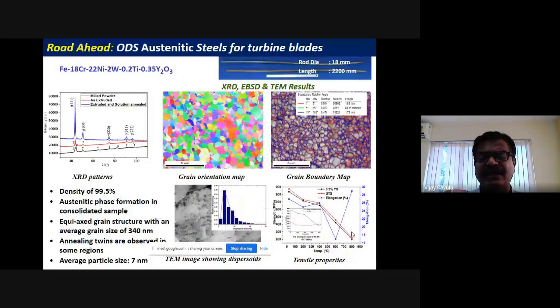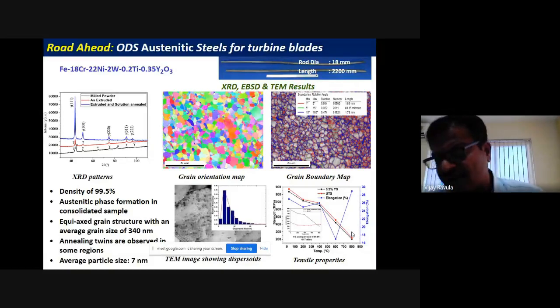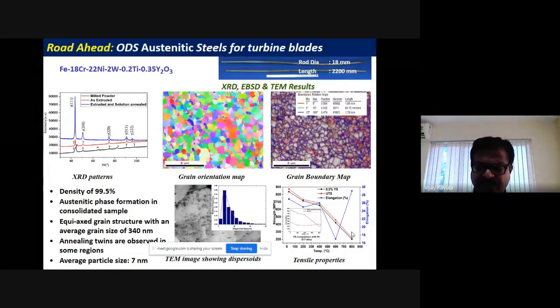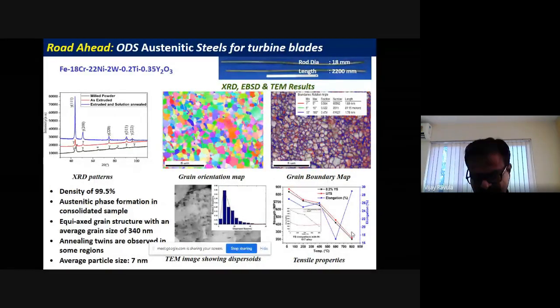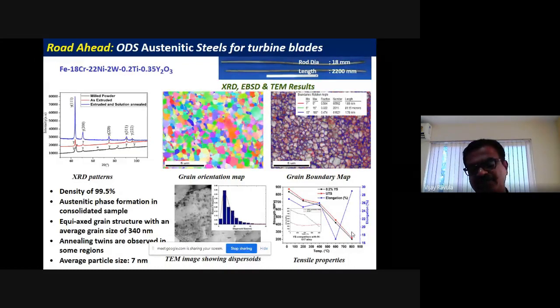And based on that, we are also looking at austenitic steels, because I was talking to you about 9 chrome, where the strength and all are okay, but the problem is they suffer from corrosion and oxidation resistance because of the lower chromium content. So if you want to use it even in gas turbines, where corrosion and oxidation are the biggest problems, we can always have austenitic steels, which have good oxidation and corrosion resistance. But austenitic steels cannot be used beyond 500 degrees centigrade. So when we put in oxide dispersions, then the strength can go up. So that's what we are working on: these austenitic steels, the future generation steels for turbine blades.